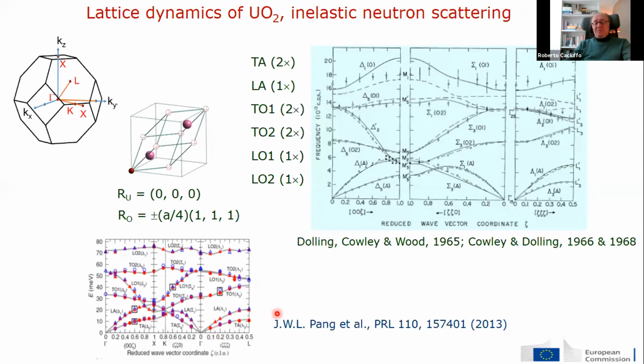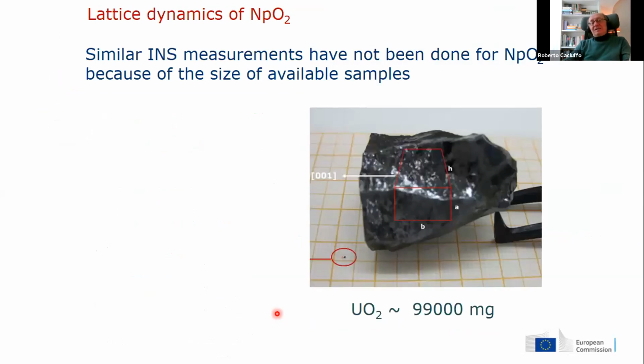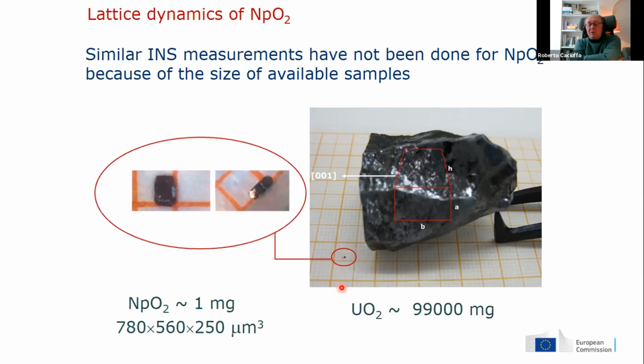In more recent years, the investigations have been extended to high temperature, above 1000 Kelvin, essentially to study the broadening of the phonons. However, similar studies have not been possible for neptunium dioxide or plutonium dioxide, essentially because of the size of the available samples. The picture here shows the crystal that we used for almost all of our inelastic neutron scattering studies, whereas this dot here is the largest single crystal available for neptunium dioxide. Those for plutonium dioxide are much smaller.